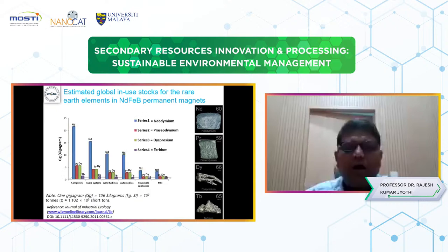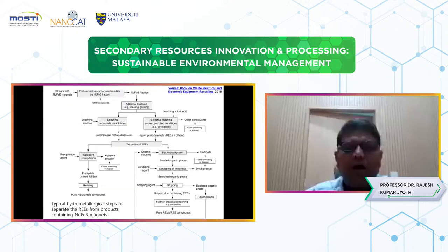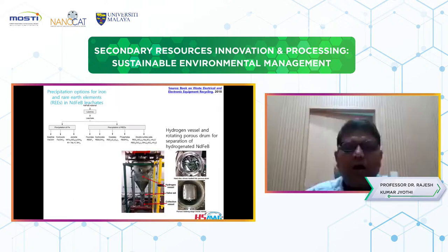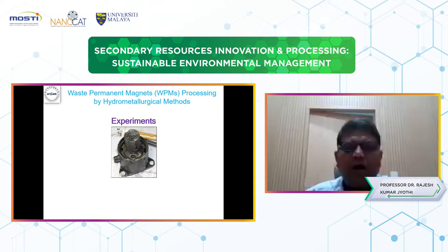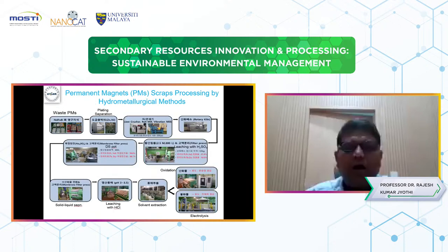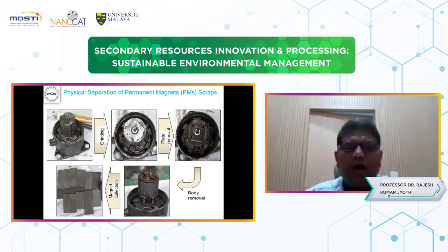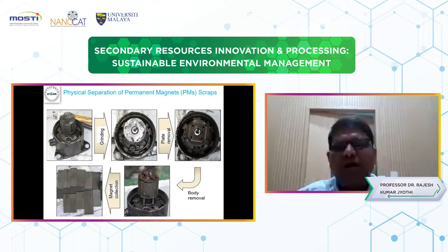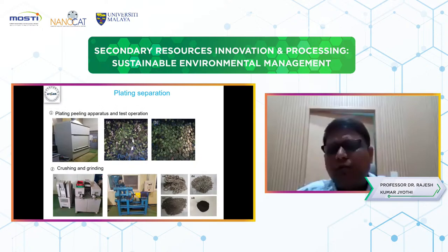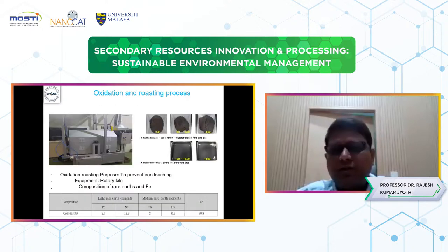You can see here, we collected small motors from AC machines. From those small motors, initially we separate them physically to get the magnet collection. After that, we perform demagnetization with high temperature. After demagnetization, we do plating peeling and testing, then crushing and grinding. After the crushing and grinding, we apply the oxidation roasting process to prevent iron leaching, using a rotary furnace. Then we apply the leaching process using sulfuric acid.